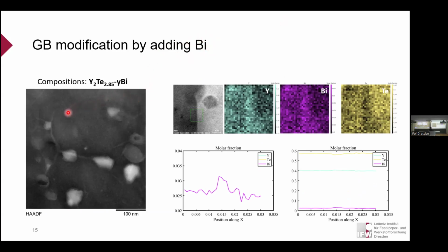And what we found is that when we add in this bismuth, we could see that bismuth does not really dissolve into the lattice. Instead, it forms these segregated particles. And simultaneously, there is also a formation of this line structure, line profile. You can see there is also some contrast along these grain boundaries. And this, of course, changes the microstructure fundamentally.